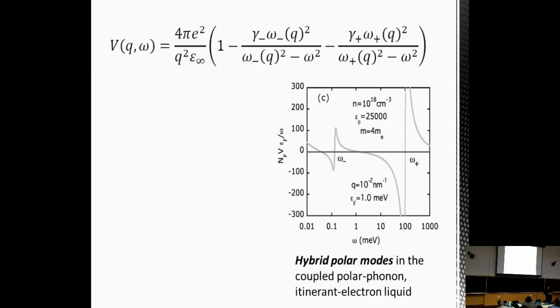And these new modes we call omega minus and omega plus. And with those are what we call hybrid longitudinal polar modes. And they're shown here for a metallic density of 10^18 carriers per cc. And you can actually measure these resonances in Raman scattering in underdoped samples.